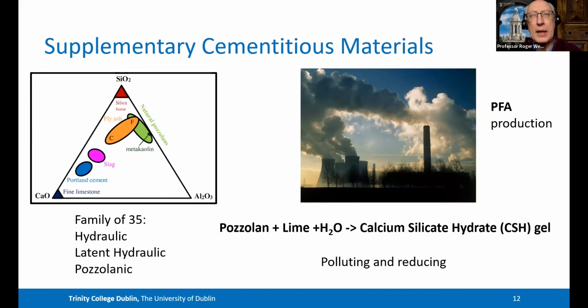In fact, within Europe, very soon we'll have a new standard for cement, which will, I think, have a family of around about 35 different types of cement. We have the hydraulic ones, such as Portland cement, which get stronger on their own. We have latent hydraulic ones, such as slag, which need a little bit of help to develop their strength at a reasonably sensible rate. And then we've got the pozzolanic materials, such as fly ash and silica fume, and the natural pozzolans. And all of these require some help because they don't become cementitious on their own.